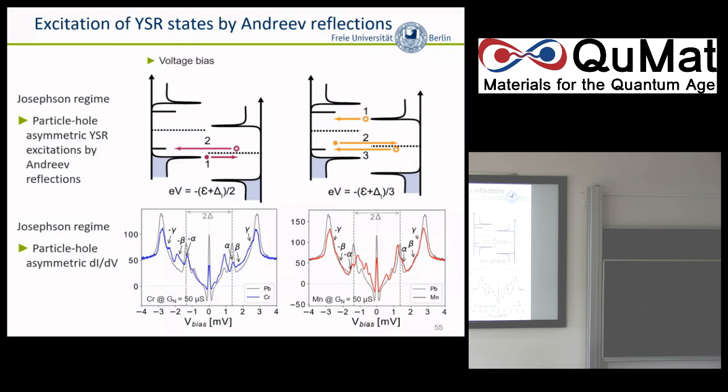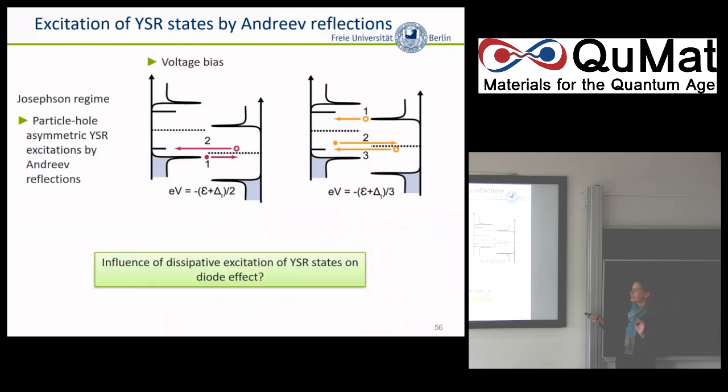Okay, so this is very important now. We have electron-hole asymmetry due to the difference in the height of the Yu-Shiba-Rusinov states. We have resonant Andreev transport through these states, obviously also when you do a current biased experiment. This is a process that takes quasiparticles, so it's the dissipative part. The dissipative part is also responsible to retrap the phase particle, and we've seen precisely the asymmetry in the retrapping current. So from that perspective, it's intuitive that you get this asymmetry in the retrapping current.